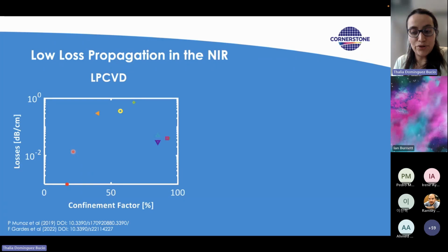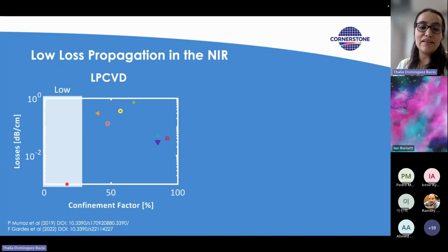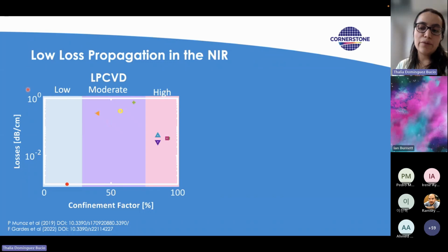So when we talk about LPCVD waveguides, we see that the losses are very low. They are less than 1 dB per centimeter. But it all will depend on the geometry that you have, if you have a geometry that has high confinement or a low confinement. Typically speaking, when we talk about LPCVD waveguides, the lower losses are achieved when you have a low confinement waveguide. What do I mean with this? I mean a waveguide that is made with a very thin layer of silicon nitride and a very wide core, which means that most of the mode is actually traveling in the cladding. In that way, you can reduce the losses from the roughness on the sidewalls, and you can lower the losses that you're seeing in your waveguide to levels of 1 dB per meter.